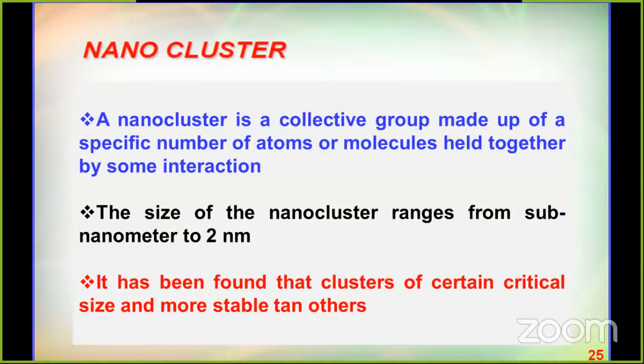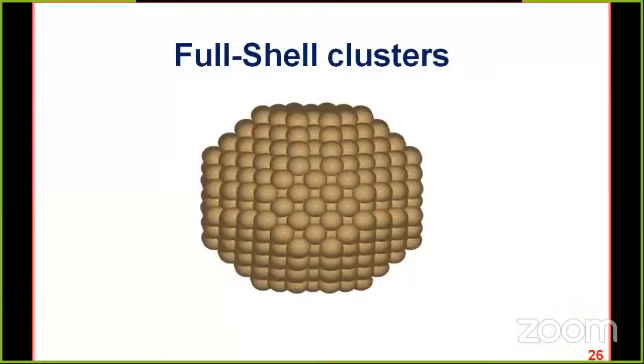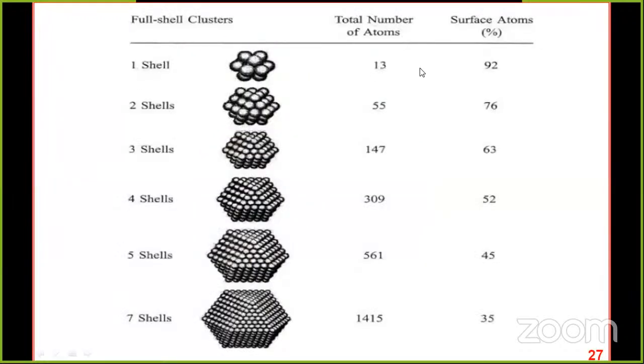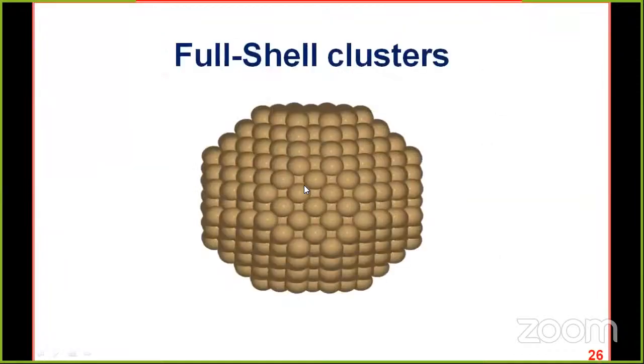Let's see about the gold nanocluster. Gold nanocluster is sub-nanometer size, 1 to 2 nanometers only. But spherical particles higher than 10 nanometers have the surface plasmon resonance band. This cluster doesn't have this. This is the cluster: 1 atom, 2 atoms, 3 atoms. So this is the atomic structure. Many atoms combined together produce a cluster size. See here, one shell, 13 atoms, 55 atoms, 147 atoms, 561, 1415, like that a shell can produce. That is called a cluster, but it is in the 1 to 2 nanometer size.